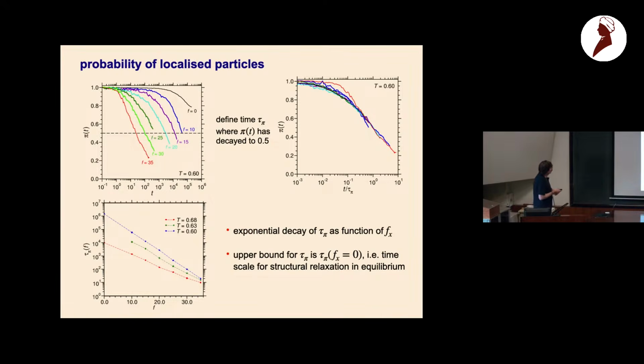When we plot this time scale as a function of force for different temperatures, we see an exponential decay. But we always have an upper bound, which is the relaxation time we would expect in equilibrium. This means we cannot have in the supercooled liquid a pure depinning scenario, because it's always restricted by this time scale, which corresponds to the structural relaxation time in equilibrium.